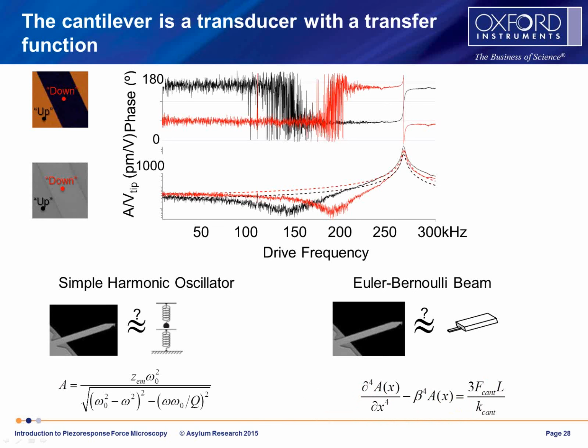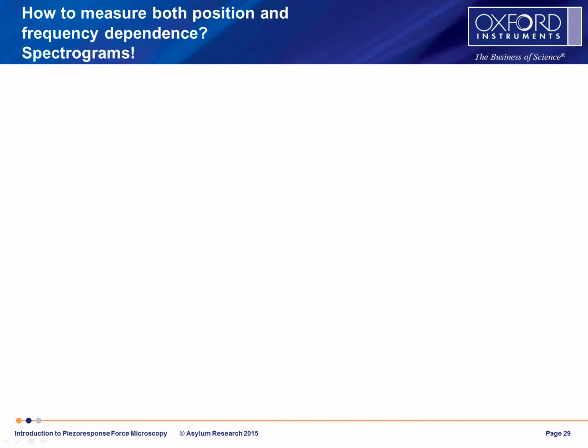But the thing to note about this, unlike the simple harmonic oscillator, in addition to a frequency dependence, which is in the time dependent term, which isn't here, there's a spatial dependence. And so this x here is the coordinate along the length of the cantilever. That's very different from the simple harmonic oscillator model. So the Euler-Bernoulli equation tells us we have to care about both position and frequency. So position of the optical detector on the back of the cantilever and the frequency at which we're driving it.